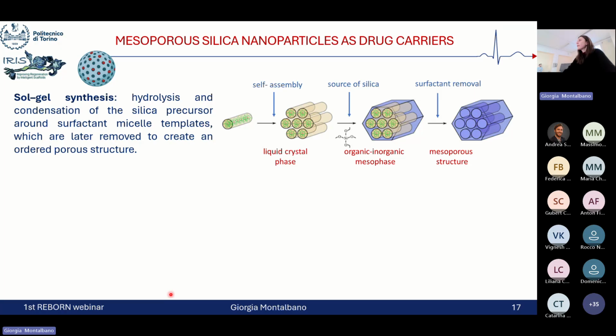So for sure, one of the most well-known nanomaterials currently used as drug carriers is represented by mesoporous silica nanoparticles. These nanoparticles can be easily produced using a sol-gel synthesis, basically just exploiting the hydrolysis and condensation of the silica precursor around surfactant micelle templates, which are later removed to create an ordered porous structure, as we can see here from the schematic.